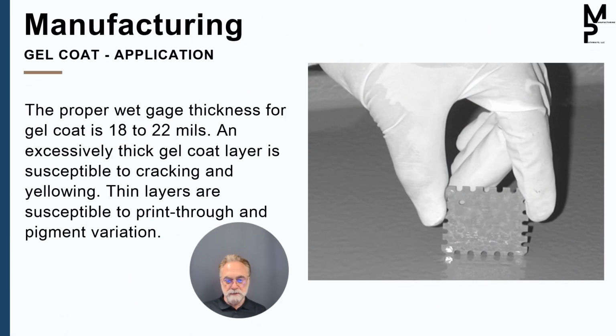Okay, so here's a mil gauge, and this is a little guy. It's got feet cut out, so when you dip it in, you'll see which feet are wet and dry, and you'll read the gauge and be able to tell how thick your coating is. We want to be at about 18 to 22 mils. That gives us the proper gel coat thickness. If we're thicker than that, we're prone to cracking. If we're thinner than that, we're prone to alligatoring, the gel coat distorting, and print through, where we see the pattern of the fiberglass through the part. So that's about the sweet spot for gel coat.